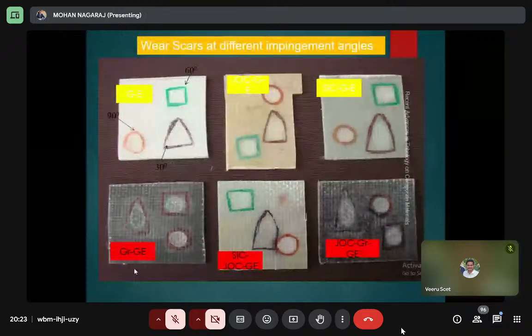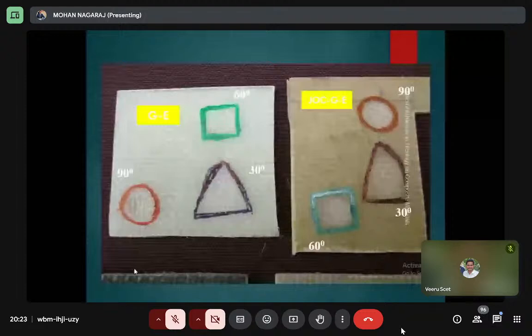For a graphite filler, the dark color is purely graphite filler, and the light dark color is JOC graphite filler. Then the JOC filled glass epoxy, the silicon carbide filled glass epoxy composite, and white is the pure glass epoxy composite we are observing. These are the erosion rate versus angle of impingement study, at 90-degree, 60-degree, and 30-degree.